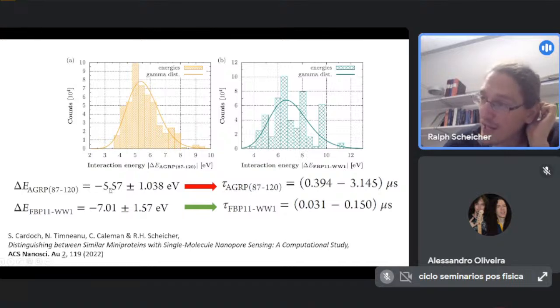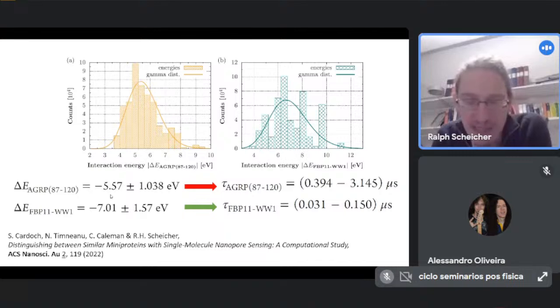And yeah, so on average, one of them interacts with around 5.57 eV with the nanopore wall, and the other with 7 eV, and quite some large standard deviation. But still, the binding energy goes into the translocation time, how fast the mini protein translocates. So actually, this results in translocation times that are on average orders of magnitude different from each other. So here we have around 394 nanoseconds, so 0.394 microseconds. And here we have only 31 nanoseconds, much faster in this case, the translocation process.